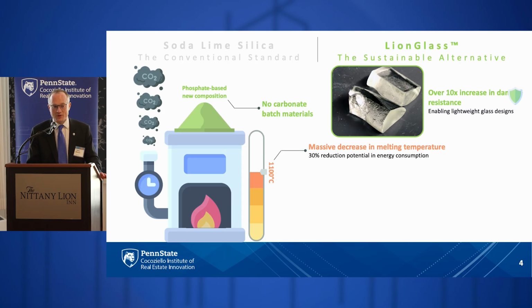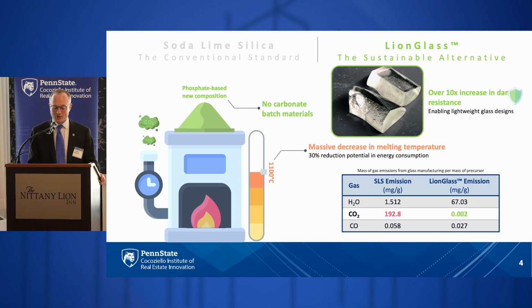We also found, surprisingly, that LionGlass has about 10 times the damage resistance compared to soda lime silicate glass, which means it takes a lot more stress in order for cracks to pop in. And this may also be a pathway toward lightweighting of glass products, since better mechanical properties mean that you can go to thinner walled products.